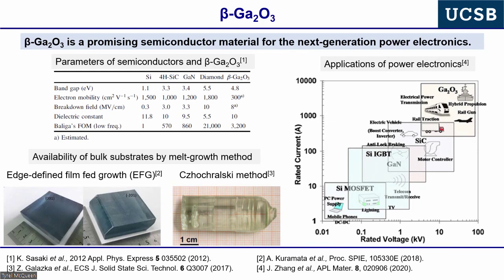Silicon carbide, which is a remarkable semiconductor, cannot be grown from the melt. There's no liquid silicon carbide from which you can pull single crystals directly. So silicon carbide is grown by essentially a sublimation-like or CVD-like process. GaN cannot be directly grown from the melt, but just in the last year or two, there's been huge progress, from work that we were involved in at the early stages, with the ammonothermal growth of GaN. But there's no direct melt growth basis for GaN or silicon, of course.